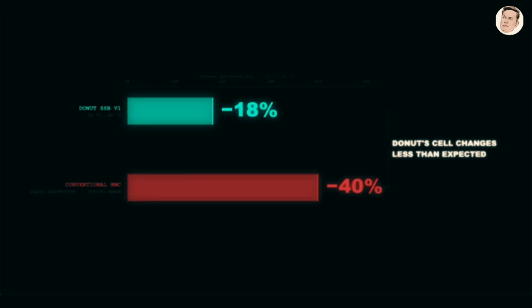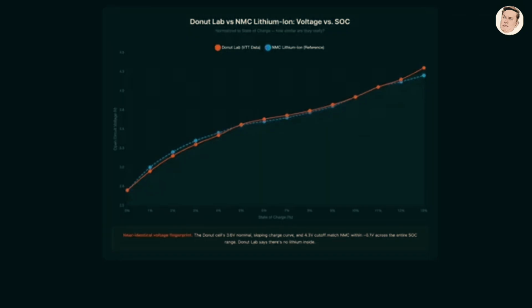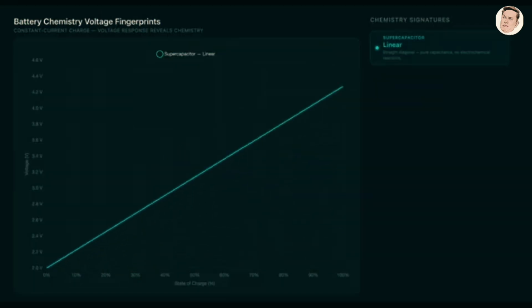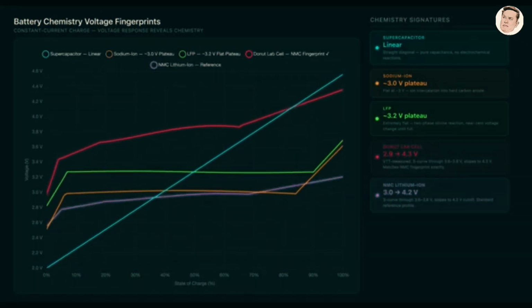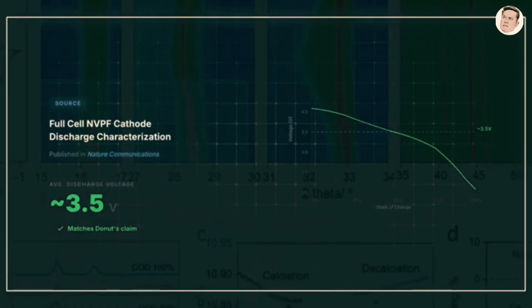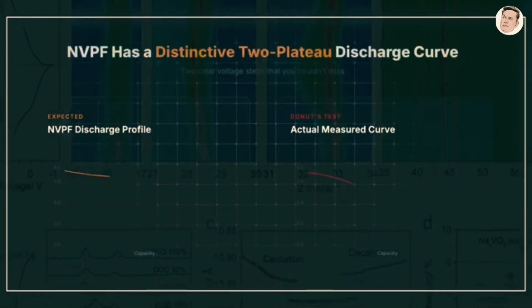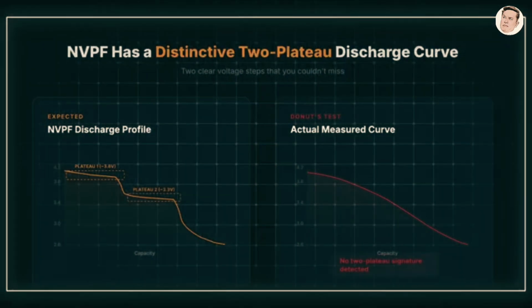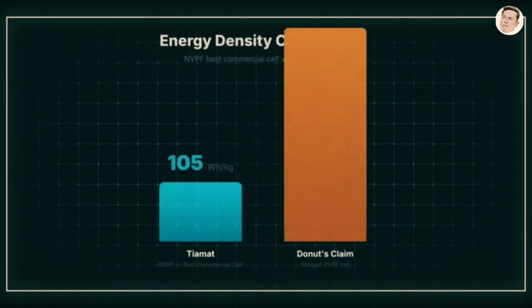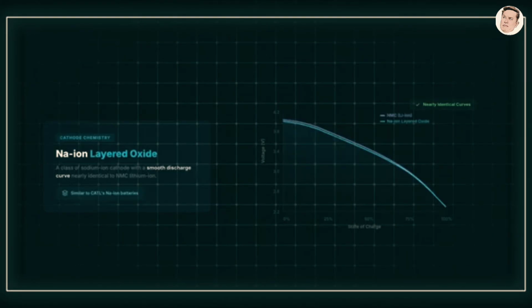It's visibly puffed in the VTT photos. And this actually makes sense mechanically. Standard pouch laminate uses a polyolefin adhesive to bond the aluminum layers to the inner polypropylene. The adhesive melts around 85.4 degrees Celsius. So, at 100 degrees Celsius, you'd expect the seal to be compromised, and it was. And Donut Lab actually calls this out. They make a point to note this. We can see that the active materials are still fine, because the cell operates normally even though the outside pouch has lost its vacuum in the heat.